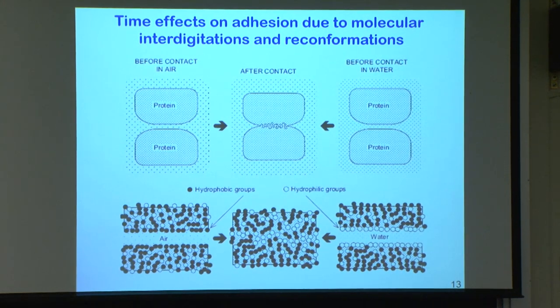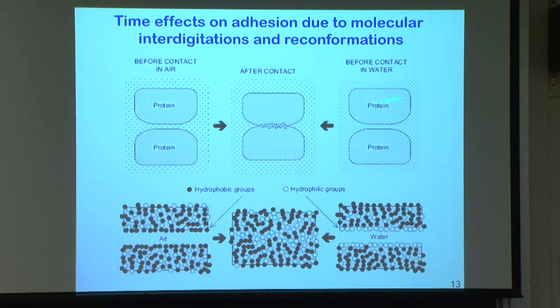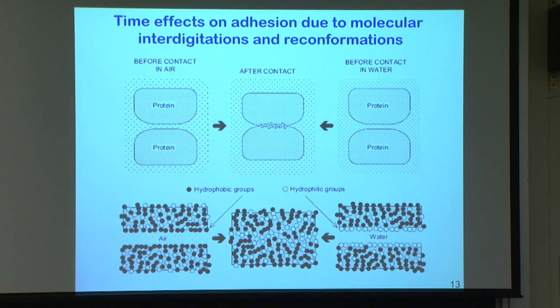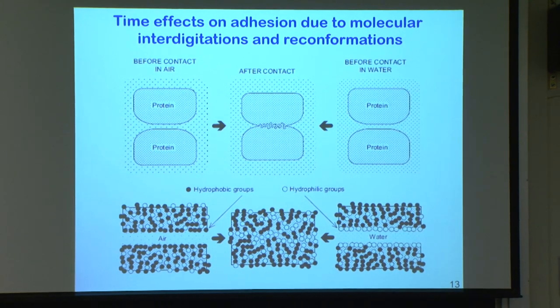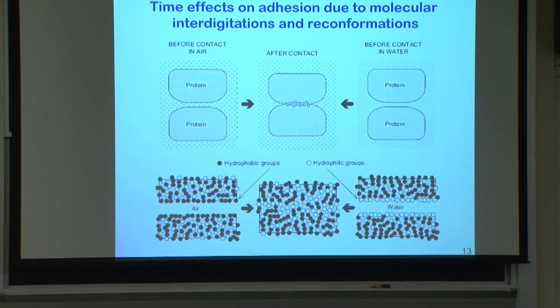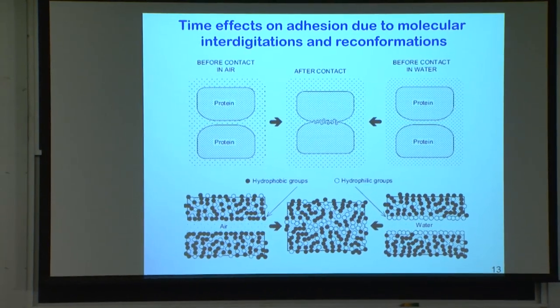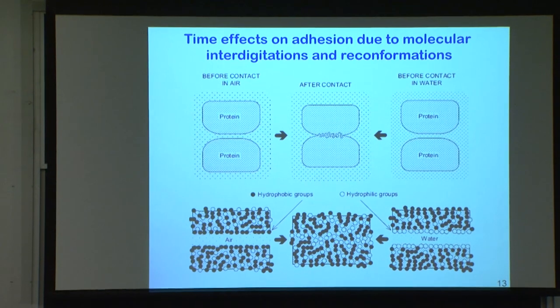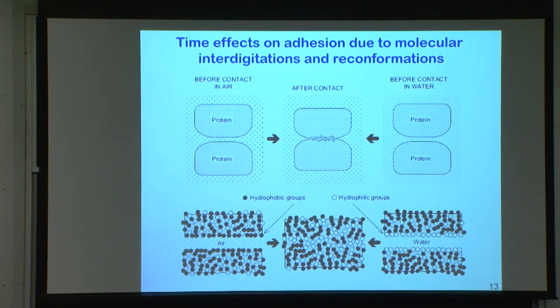This is an example that happens with proteins and polymers in general, where with time, the contact area changes, and the whole contact changes. Molecular or group rearrangements occur. Hydrophobic groups point at each other. Acidic and basic groups start pointing to each other. And with time, the interface no longer remains flat. So the adhesion in general increases with time, just keeping things in contact. And these times can take milliseconds, or they can take minutes or hours.